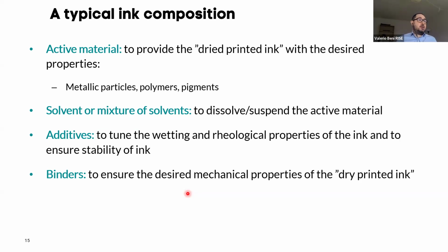Often these two components are not enough to create a very good ink. As I said, the performance of some of the manufacturing technologies is strongly dependent on how the inks interact, for example, with the surface, their viscosity properties, and their surface tension. So in the solvents, you will have a series of additives. These additives could be surfactants, for example, which are used to tune the wettability. There could be thickeners, to modify the rheological properties of the inks, and also stabilizers in order to ensure the stability of the ink itself. And finally, but not least in importance, binders.